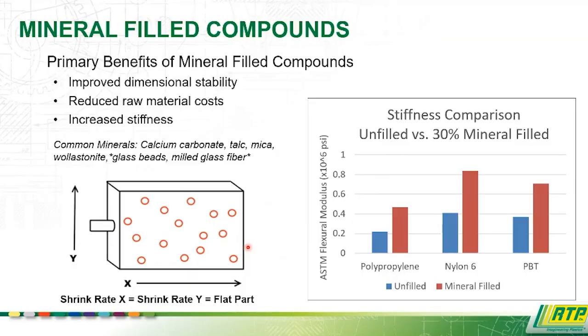So I mentioned when you have the reinforcements, your flow versus cross flow gets affected. What these low aspect ratio fillers do is actually reduce that differential in shrink and give flatter parts. So with those types of low aspect ratio fillers, you get improved dimensional stability. A lot of times minerals are going to be low cost, so you actually can pull some material cost out. And a lot of times you'll actually get an increase in stiffness depending on exactly which mineral you're using. So take, for example, some different semi-crystalline resins with 30% mineral. You can actually get around a 2x increase in your stiffness with that type of thing, along with the benefits of the dimensional stability.